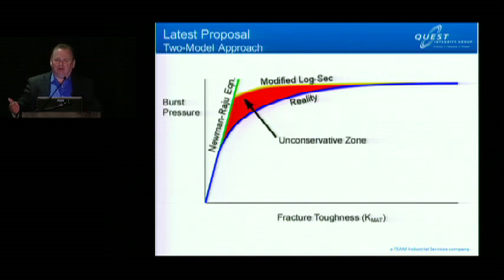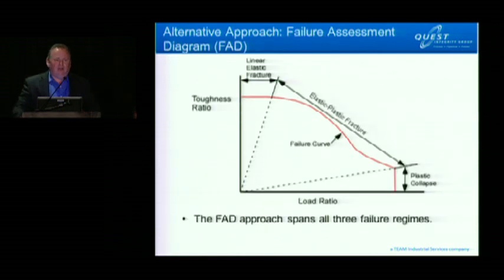You still have an uncertainty zone. They've reduced the size of the red zone, but haven't eliminated it entirely, because you have one equation for linear elastic, another equation for plastic collapse, but then the elastic plastic regime, which actually is where most pipelines live, is not predicted correctly, and it's unconservative. So what do you do about that? Well, there's the current state of the art in fracture mechanics. Most codes and standards use something called the failure assessment diagram, which I won't go through in detail, but it does predict reasonably well what happens.